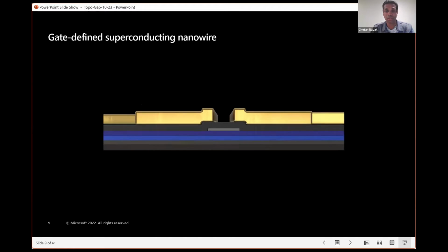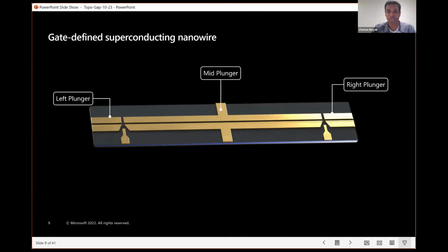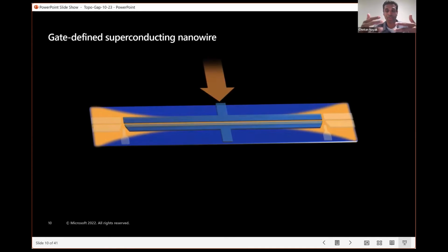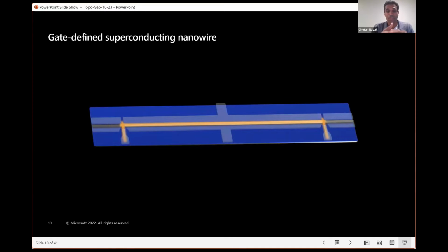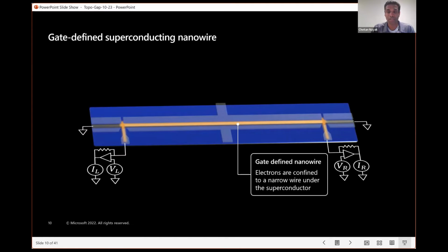The purpose of gates will be clear shortly when we take a look at a top view, okay? And we see in the top view, the gates are actually separated or divided into 3 sections, okay? A middle, a right, and a left. And what these gates do is, when they're energized, meaning we put negative voltage on them, they deplete the 2-dimensional electron gas, they deplete the indium arsenide quantum well almost everywhere. Everywhere that's not covered by aluminum is fully depleted. And out on the sides, where it is covered by aluminum, it's also depleted. But underneath the middle section covered by aluminum, it's not fully depleted because the aluminum partially screens the electric fields from the gates and leaves some density down there.